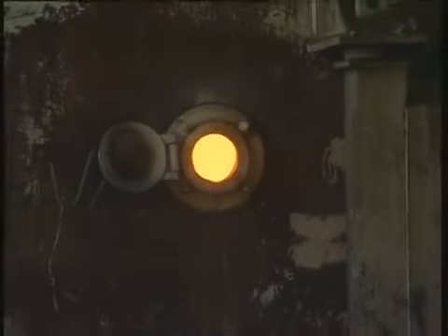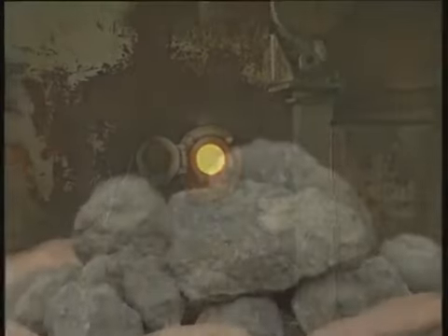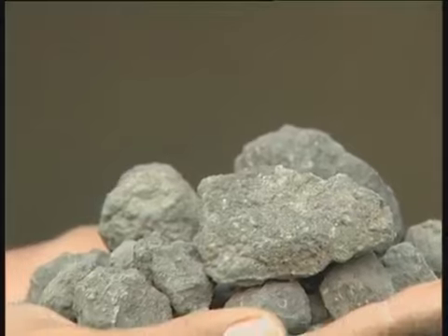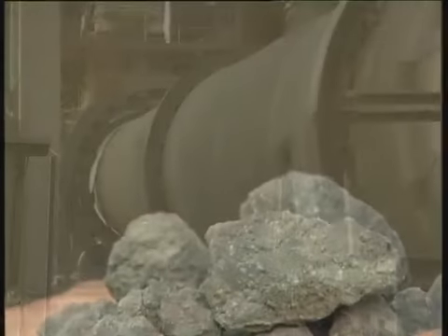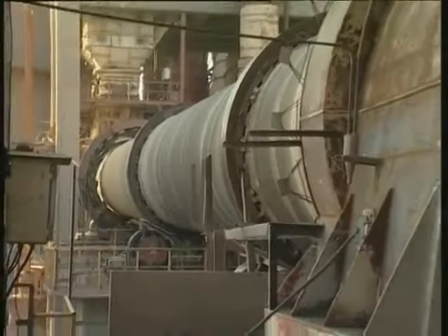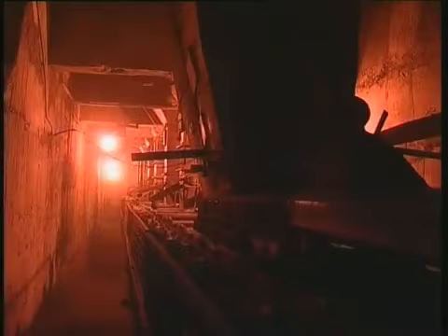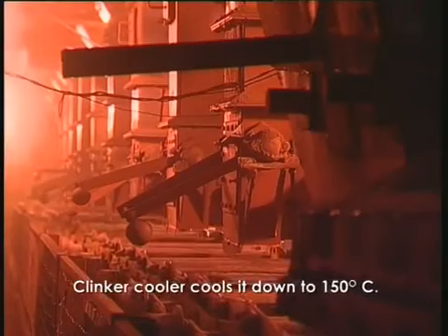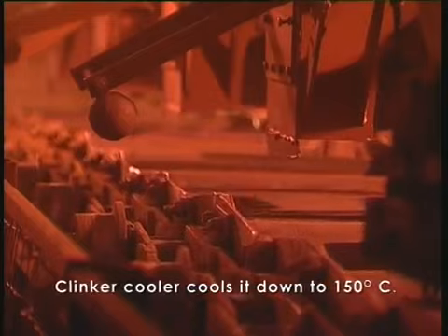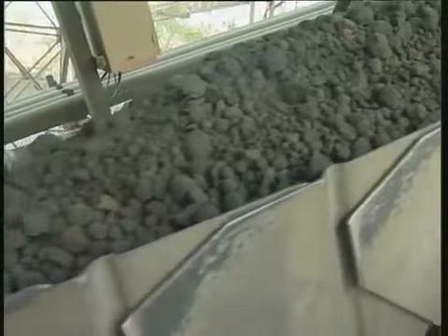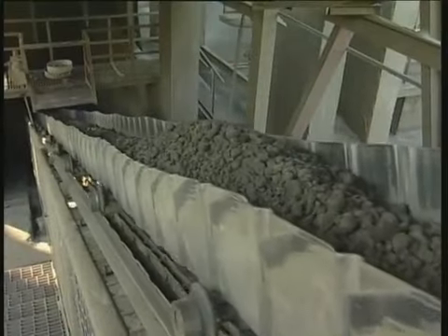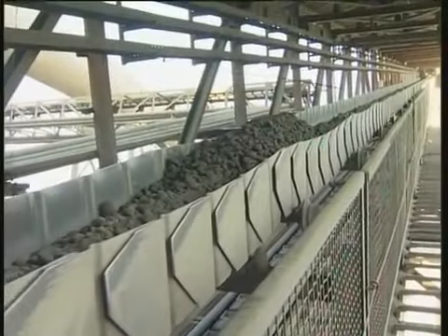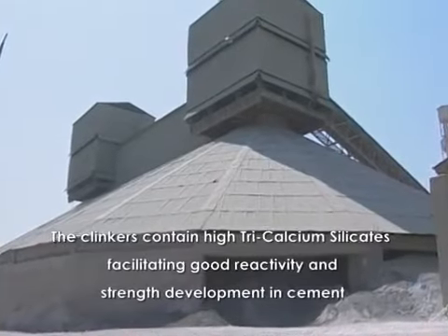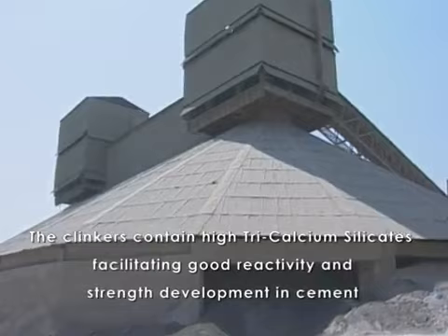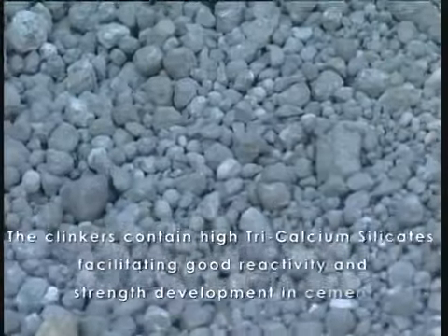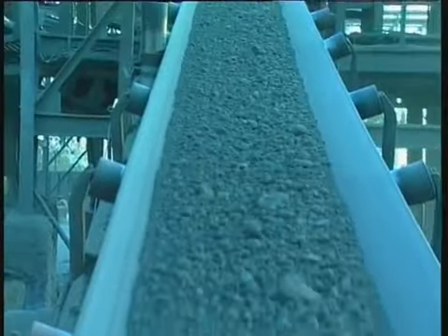At the hottest part of the kiln, a 1870 degree centigrade flame converts the partially molten raw material into pellets called clinker. The rotary kiln discharges the red-hot clinker into a clinker cooler where it cools down to 150 degrees centigrade. The cooled clinker is sent to the clinker stockpile where it is stored until needed. The clinker is now ready for the final process of cement production.